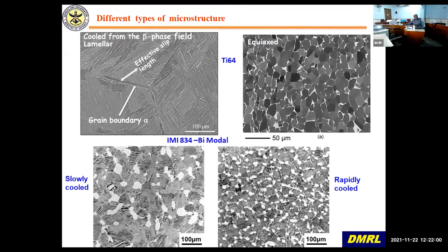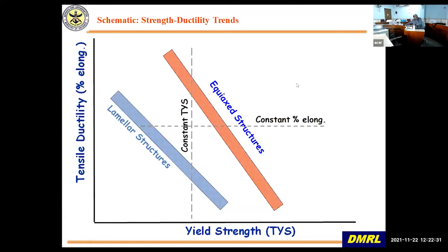So here are again the same microstructures. This is a beta treated structure. It has big beta grains because the diffusivity in beta or BCC is higher, so you get large grains. In the beta treated structure, whereas in equiaxed or bimodal, you can see you get a much finer grain size. So for fatigue kind of application, this kind of microstructure is much better, and this kind of equiaxed microstructure is good for formability applications. I'm just showing you here the tensile ductility, that is percentage elongation versus yield strength.